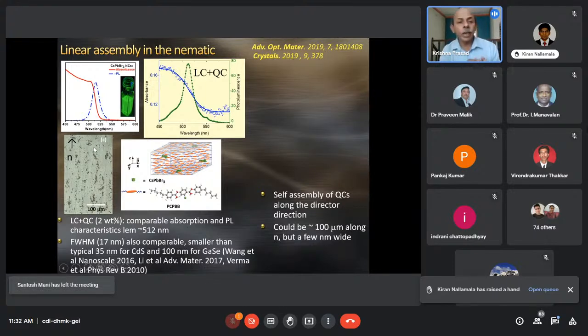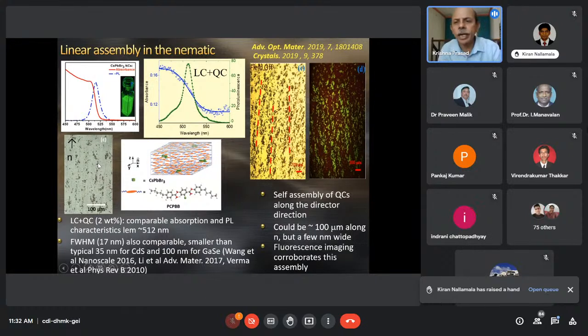So now in the liquid crystal architecture, along the director, the quantum cuboids are going to organize themselves to be along the direction itself. This image is taken with polarizing microscopy, and to prove our point that these dark regions that you see are indeed quantum cuboids, we also took a fluorescent image of that, and that is clearly seen here. This is the polarizing optical microscopy without the fluorescent light, and this is with the fluorescent light, and you can see that actually these linear assemblies are coming from the quantum cuboids.